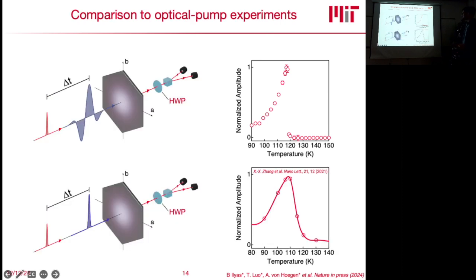Where we got a little bit discouraged then is that other people also saw this. And they saw it not using terahertz excitation, but with optical excitation. So they're basically quenching the ground state, which translates into a temperature increase. And so what we wanted to do is non-thermal engineering of this material, but this seems to be a very thermal process.